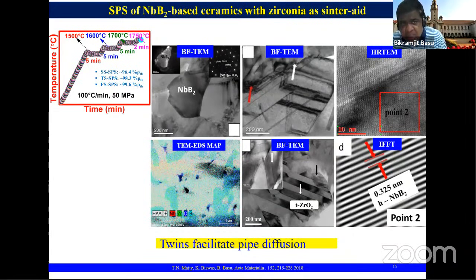As a next step, we have developed these very recently. We have developed these niobium diboride-based materials. Again, following a similar processing strategy, here we have adopted the spark plasma sintering technique by holding this niobium boride, which has been milled with zirconia milling media, at different temperatures up to 1750 degrees Celsius.